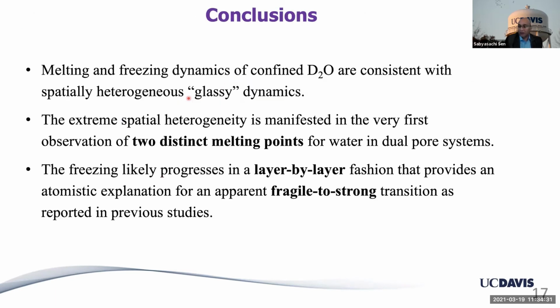So in conclusion for this part of the study, I would say that we have seen strongly spatially heterogeneous glassy dynamics of confined D2O. Even in its melting point, we have seen two melting points in interconnected pores, which was something totally unexpected to us. And this extreme spatial heterogeneity actually translates into a layer by layer freezing process, because every layer, as a function of its distance from the center or from the periphery of the pore, probably has a different kind of structure. And these structures freeze at slightly different temperatures. So it's a continuous layer by layer process, which eventually gives rise to this fragile to strong transition.